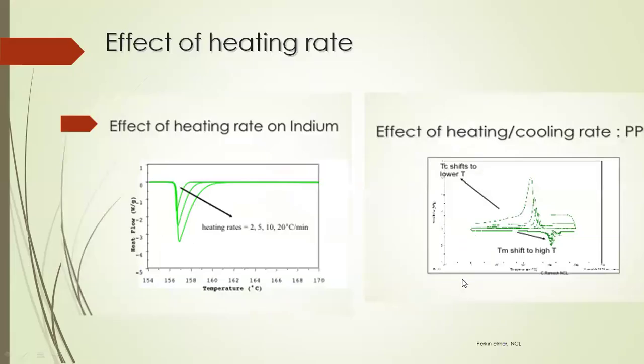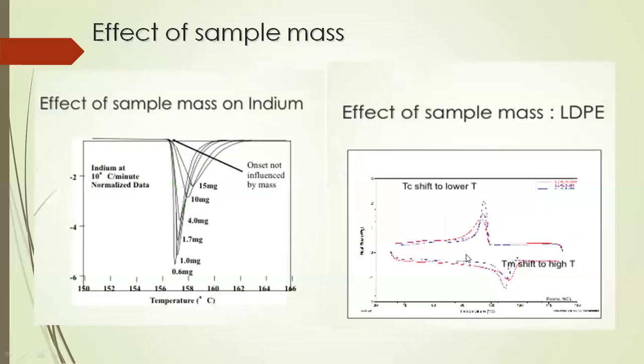Again, the factors which affect our DSC: also heating rate. In case you increase the heating rate, your melting curve looks like this. I mean, Tm shifts to a higher temperature in the case of polymer. In the case of metal, you get a similar melting temperature because in metals you get the onset of melting as the melting. But in the case of polymers, our melting temperature shifts to a higher temperature and our crystallization curves also shift lower with respect to temperature. Again, sample mass. If you increase the sample mass, you get different melting curves and different crystallization curves in DSC also.